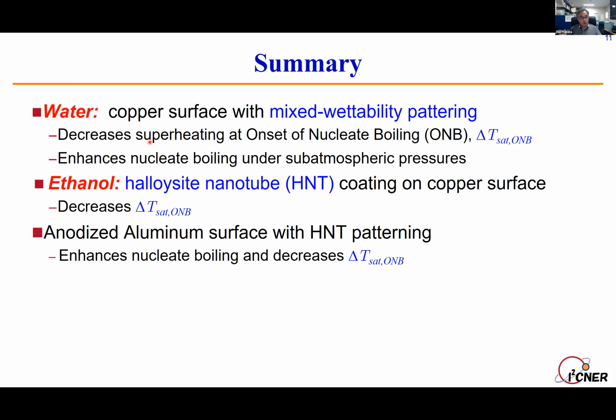So for water, we first used a copper surface with mixed wettability patterning, and this surface decreases superheating at the onset of nucleate boiling, and also enhances nucleate boiling under subatmospheric pressures. For ethanol, we used a halloysite nanotube HNT coating on the copper surface first, and it significantly decreases the onset of nucleate boiling temperature. For the anodized aluminum surface, the HNT coating pattern enhances nucleate boiling and also decreases the surface superheating at the onset of nucleate boiling.